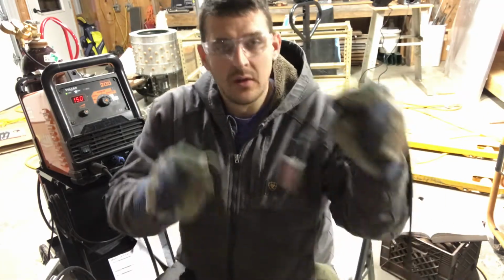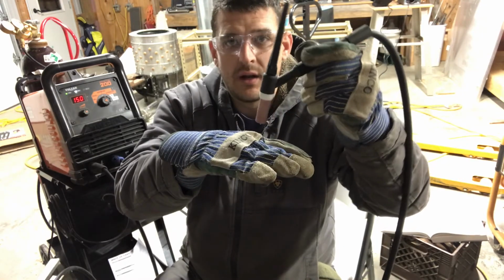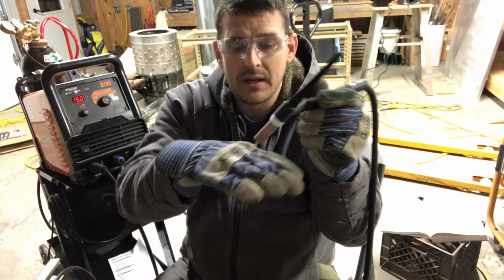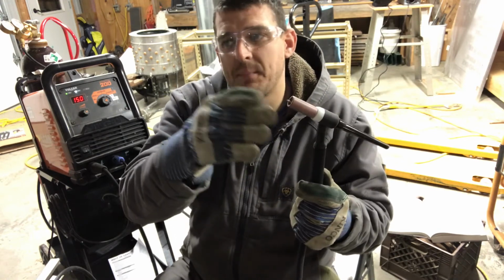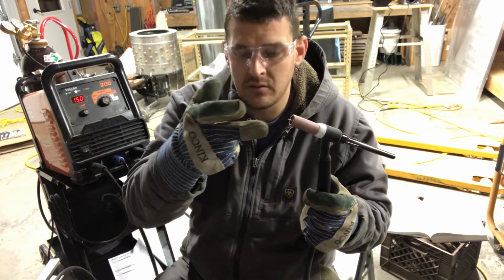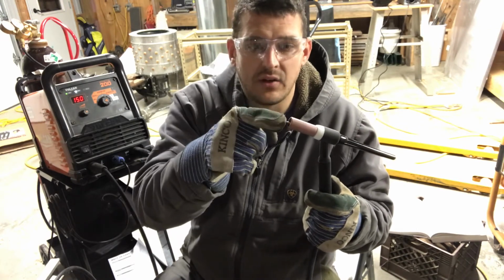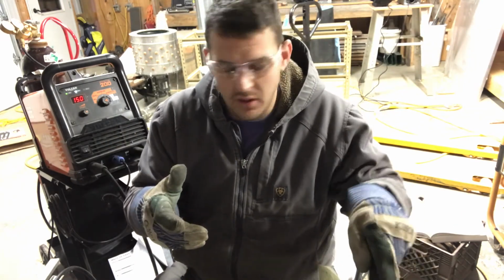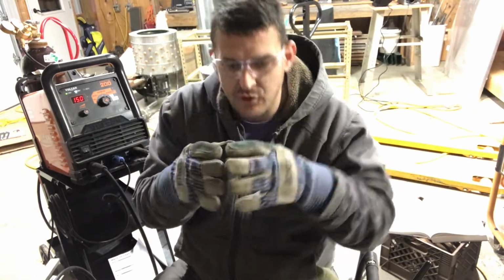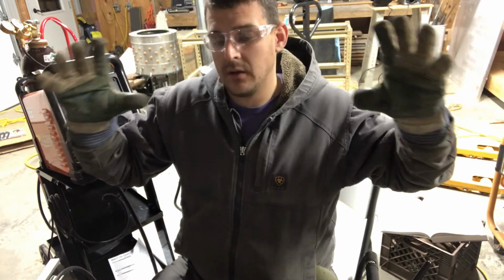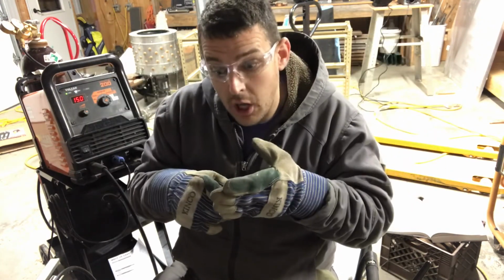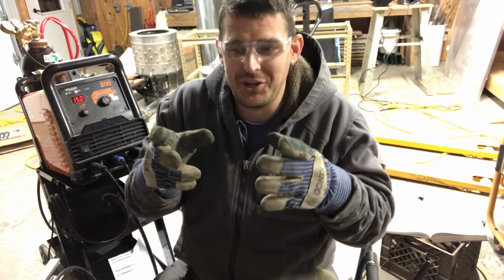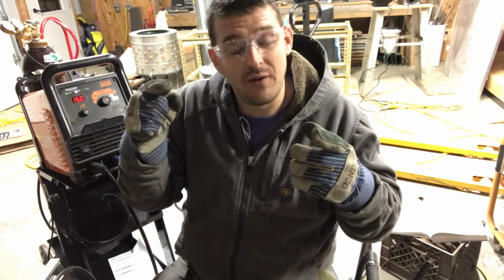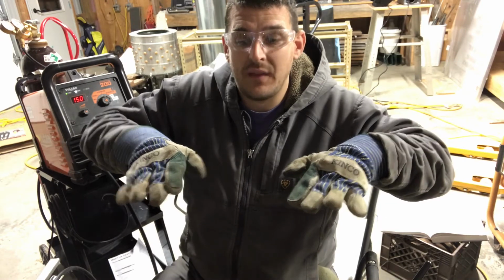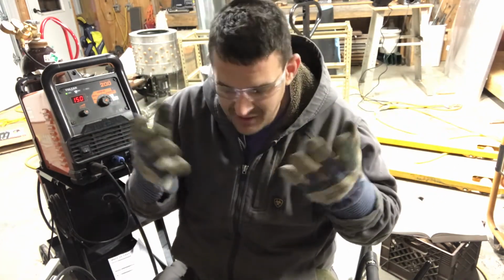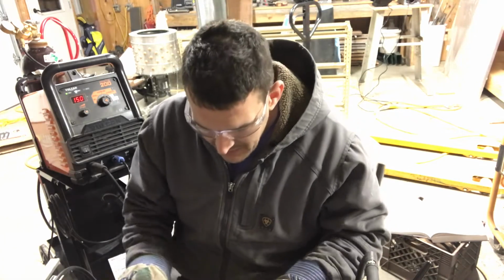I also found that if this is the workpiece and it's straight into it, I'm actually getting a lot better results, because if you get the tip in the molten pool, then you're putting tungsten in the weld, and it makes it impure. So you've got to be just right. If you're too far away, you're just blasting out this big, wide arc, and you're not getting this focusing. If you're too close and the pool is too big, then you're getting crap on it. If you don't have enough juice and you're melting it out flat, then your pool is tall and you're getting it in the tip. So there's so many things going on all at once that it's kind of hard to do that.